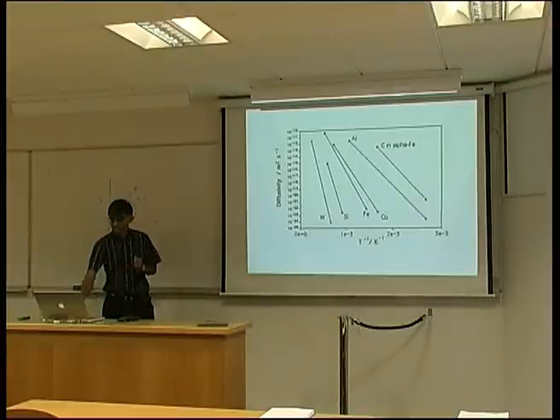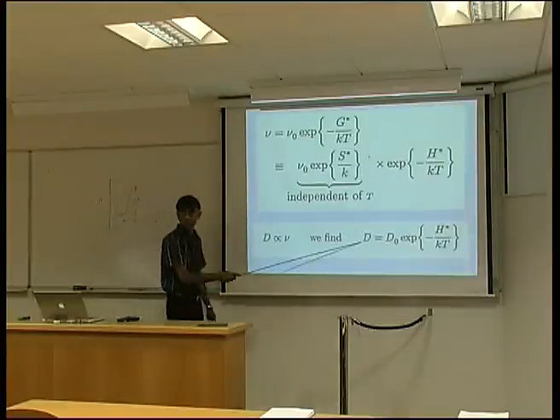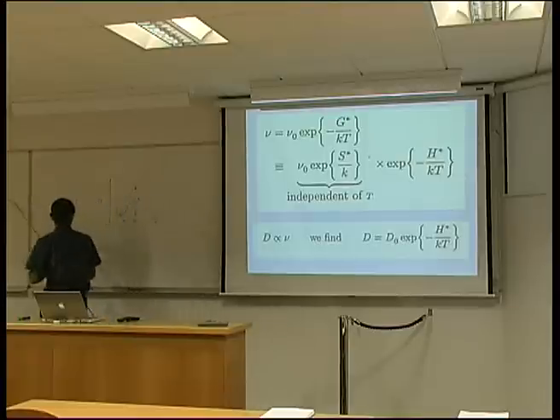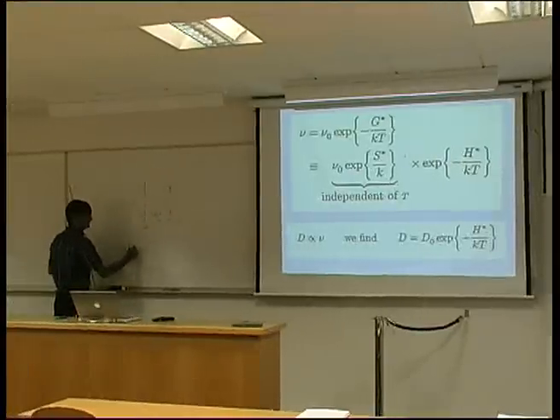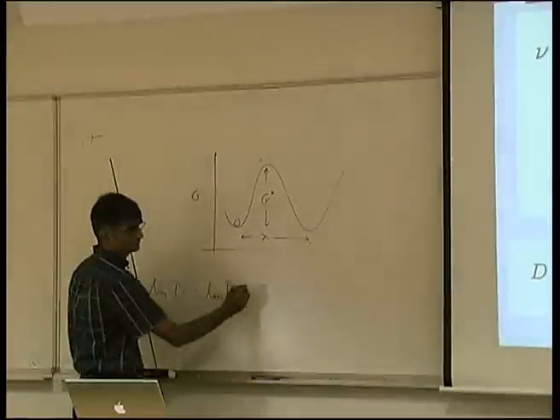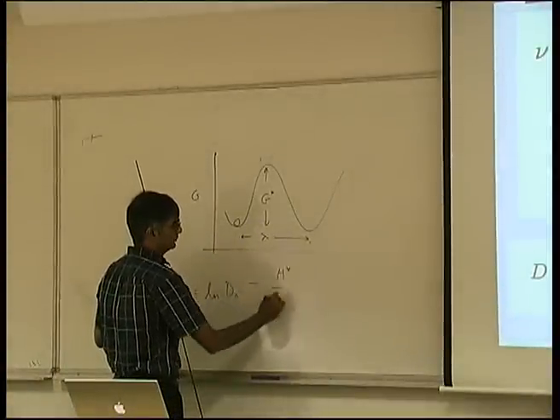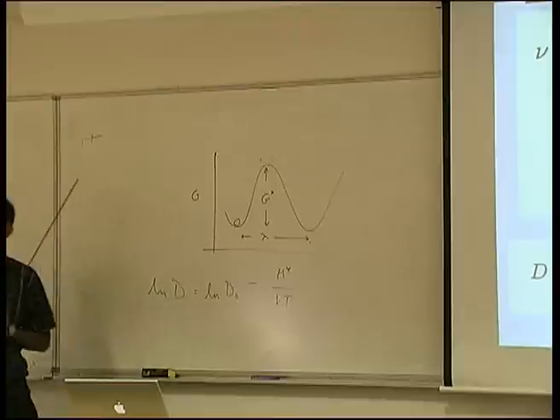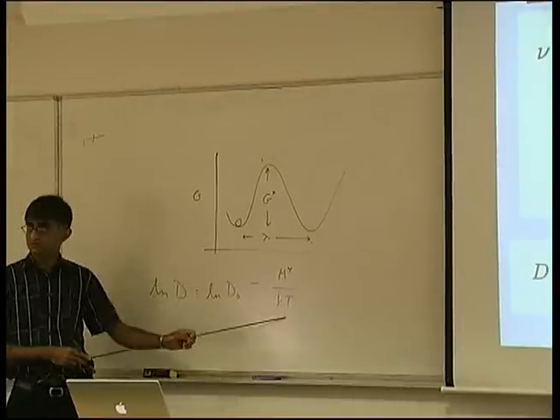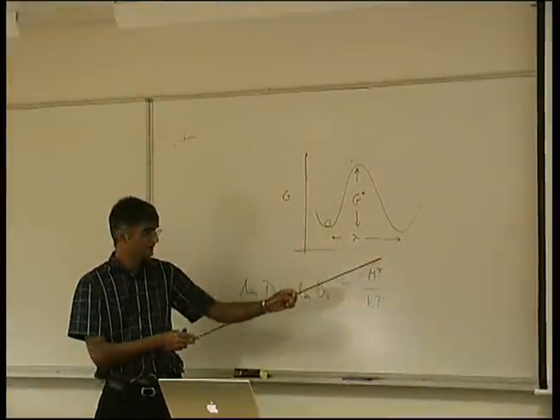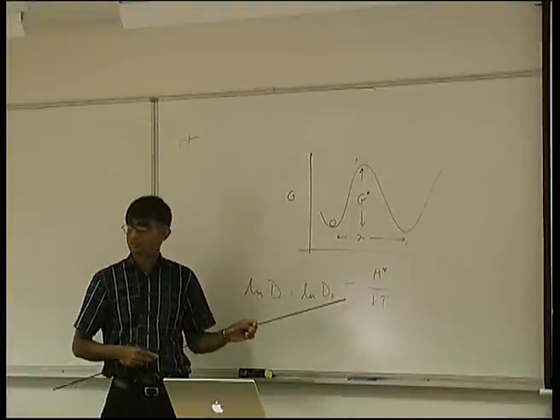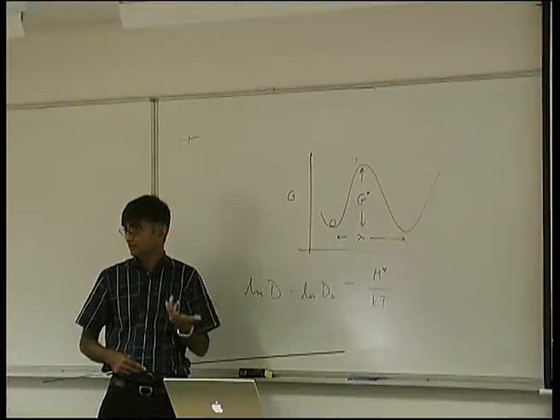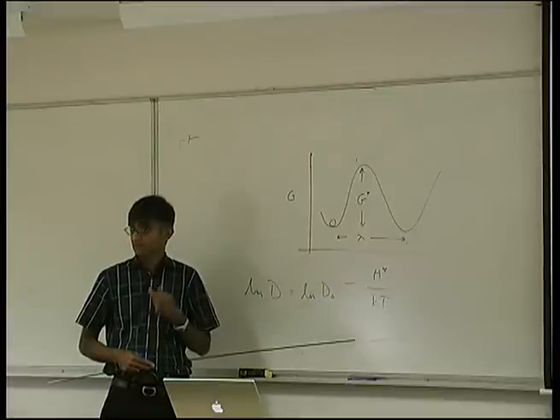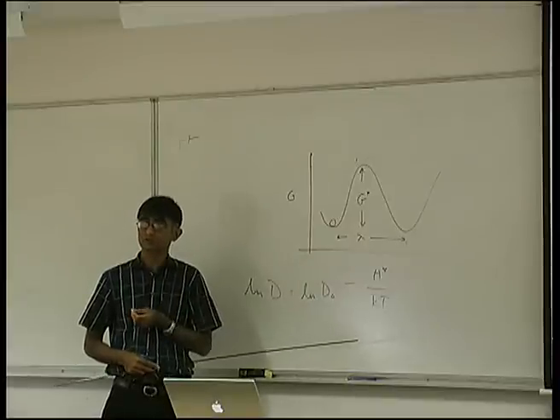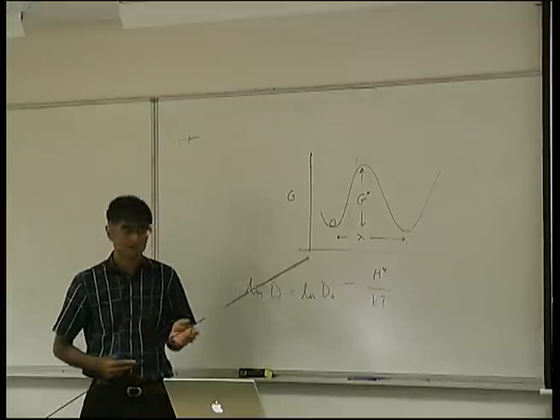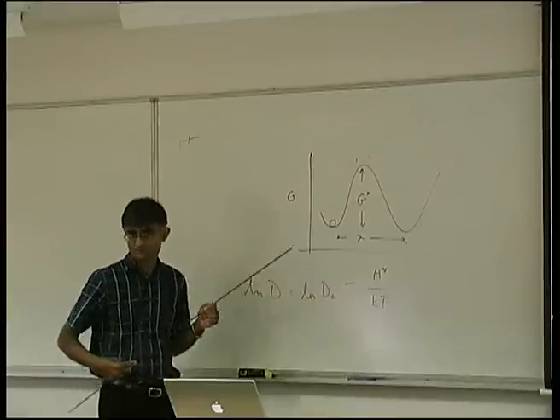And if I take the natural logs on both sides, then this will become the log of D is equal to the log of D naught minus H star upon KT. So if I plot the log of the diffusion coefficient versus 1 upon T, then the gradient is given by minus H star upon K. So I could derive the activation energy, activation enthalpy, by measuring the diffusion coefficient as a function of temperature. And similarly, I can get D naught from the intercept.